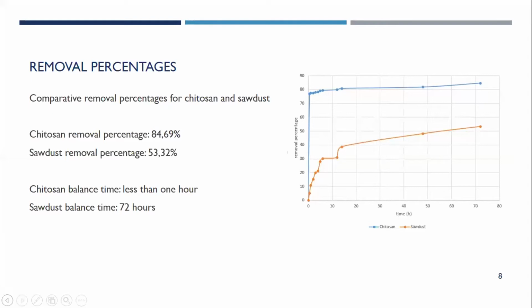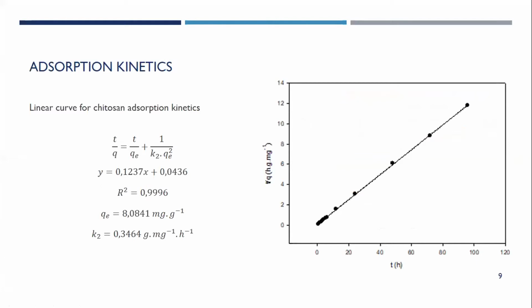As was described before, this experiment also shows us the balance time for each adsorbent. Chitosan's balance time was shown to be less than 1 hour, while Sawdust balance time was 72 hours. On to the adsorption kinetics. Here we can see the linear curve for Chitosan adsorption kinetics, which follows the equation shown. At an initial concentration of 50 milligrams per liter, the Chitosan adsorptive capability was 8.0841 milligrams of dye per gram of adsorbent, and the constant for pseudo-second order adsorption rate was 0.3464.